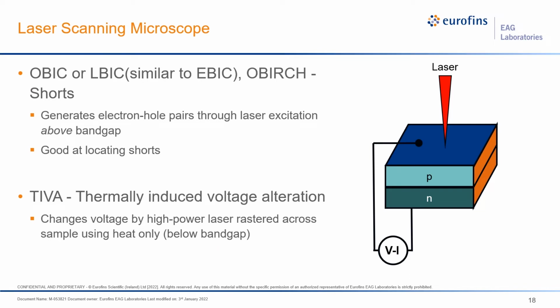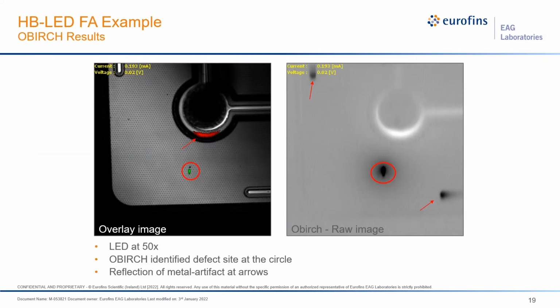And so OBIRCH stands for optical beam induced resistance change. In this case, we're going to be using a laser that's generating electron hole pairs through excitation above the band gap. And this is particularly a good technique for locating shorts. There's another mode called TIVA, where we're looking at the voltage change by rastering a laser. In this case, it's typically below the band gap, and then we're only looking at changes in the voltage due to heating in the sample alone. So in this case, we're using this OBIRCH situation, and we get this mapping of the resistance change across the sample itself, and we see that we have this very distinctive low point here where the resistance falls.